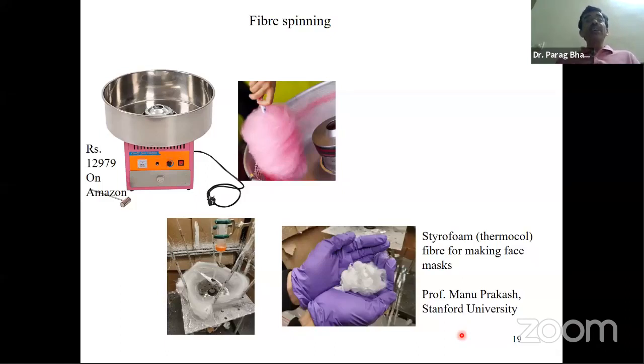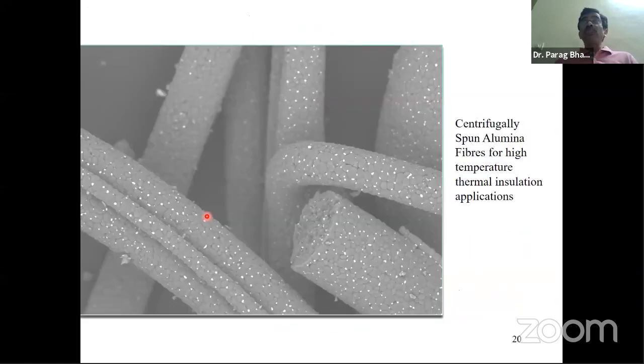Now, the other reason why I showed this was, we developed a similar machine in our lab. We didn't buy it, and we made ceramic fibers, high temperature fibers. I'm going to show you pictures. The ceramic fibers that we make have melting points of the order of 2000 degrees. So what is the use? We use these ceramic fibers to make high temperature thermal insulation for making furnaces.